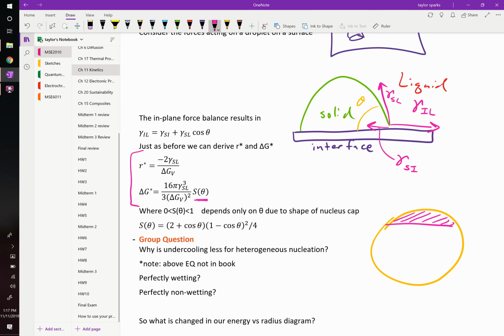S of theta is a number between 0 and 1. In worst case scenario, you have homogeneous nucleation. If S of theta equals 1, then your wetting angle is so severe that it's like a perfect sphere, you don't get any benefit of heterogeneous nucleation. But it can also be less than 1. It can go all the way down to 0. And that's going to give you a big reduction in your activation energy for nucleation. Like, look at your delta G star expression. It's the same as before, except it's multiplied by a number between 0 and 1. So you can get huge reductions in your activation energy that you need for nucleation to happen.